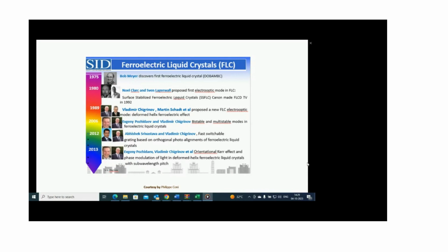But unfortunately, it was not good, not stable, mechanically unstable. Defects appeared when you have mechanical damage and so on. So since 1989, together with my colleague and friend Martin Schadt, we proposed first deformed helix ferroelectric effect, and then together with my colleague Evgeny Pozhidaev and Professor Abhishek Srivastava, we demonstrated many different electro-optical modes based on photoaligned ferroelectric